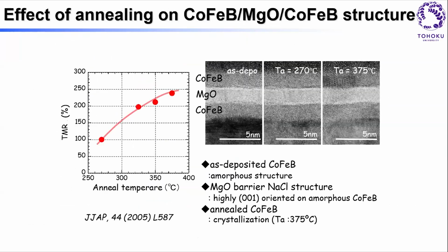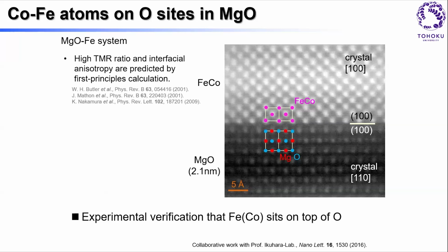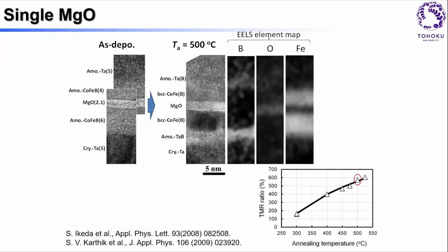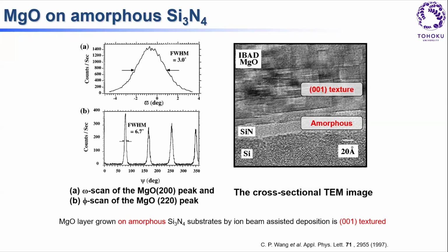So we got lucky because the nature of this material system is such that after annealing on any substrate, we get the crystalline structures that we need to have. So this is a TEM micrograph, just to convince you that it's indeed an epitaxial relationship at the interface. Okay, I'll skip this part.